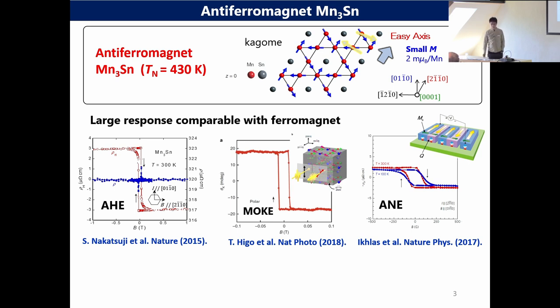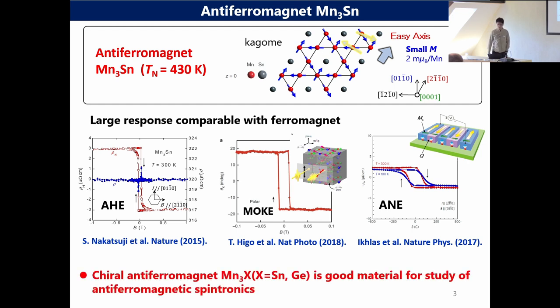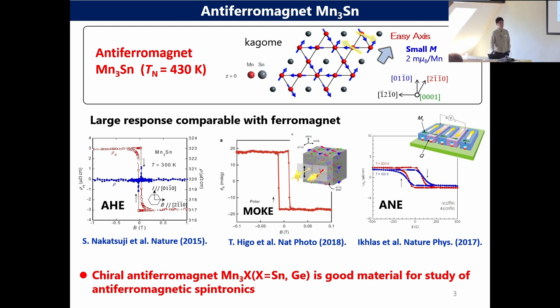This large response is caused by the very large Berry curvature of this material. An important thing in the experiment is that the magnetic switching field is very small. In the bulk case, it's around several hundred Oersteds, or around 100 Oersteds. So it means that even in this antiferromagnet case, we can control the magnetic state by using a small magnetic field. In that sense, this kind of antiferromagnet material is a very good material for studying antiferromagnet spintronics — for studying the fast dynamics in the antiferromagnet.